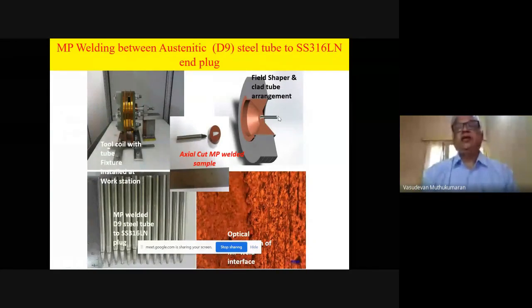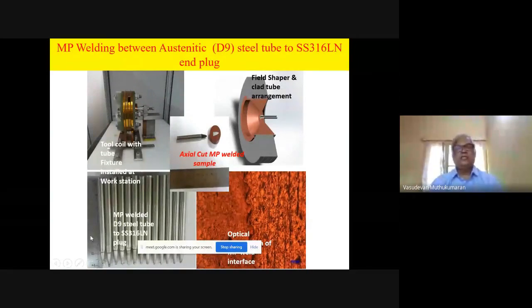Then here we have done D9 austenitic stainless steel to 316 end plug welding. You can see the welded parts. We optimized the process parameters. You can see the bonding and the entry. It's wavy welds, similar to explosive welding, because of high impact. Due to high impact, the bonding takes place by plastic deformation. You can see the wavy interface. There is no melting involved. So we could successfully optimize and fabricate.